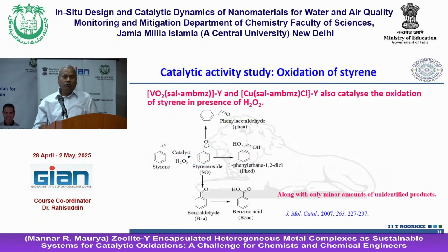Okay, then we studied another reaction, which is the styrene. Styrene gave us 5 different products. What we expected was that styrene should give styrene oxide, the epoxide, best, not other products, but definitely we were not able to optimize to get maximum product like styrene oxide. It was not possible. The reason is that the oxidant ultimately oxidizes styrene epoxide to other products. Okay, but it worked, and we were able to find all 5 different products.